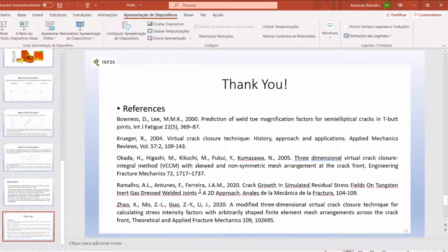As far as I understand, you simulate the effect of residual stresses that are generated by overloads. Did you analyze the effect of residual stresses generated by the welding process? Yes, we have made two-dimensional simulations with the effect of welding stresses, the stresses generated by welding. But when we go to make the simulations in three dimensions, it is very hard, and this is intended as future work.